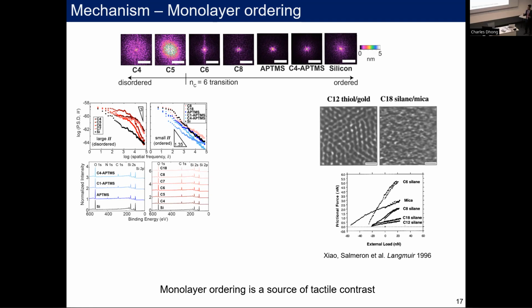So overall, I wouldn't say that it's a 3-carbon difference in length that really leads to this ability to tell surfaces apart. It's more the idea that you can use differences in monolayer ordering to create tactile contrast. So however you achieve that, whether by getting longer carbons or substituting in nitrogens for carbon, will lead to the same effect, which is what we see.